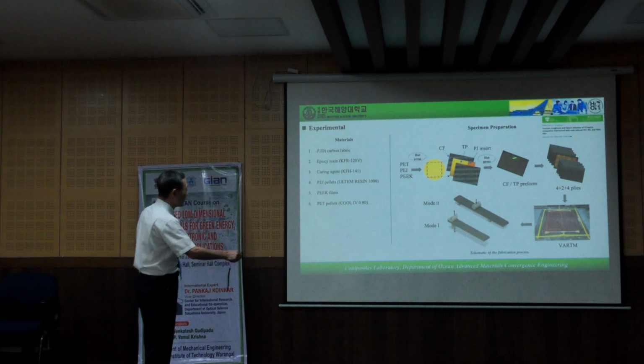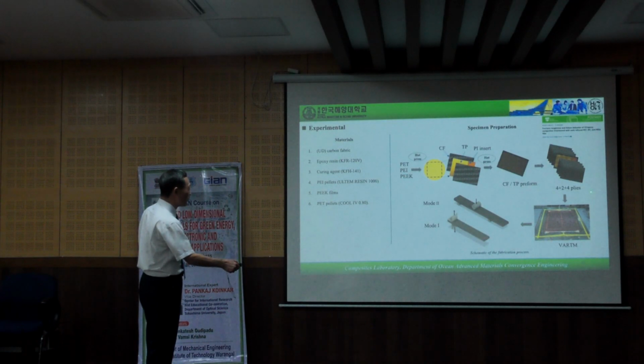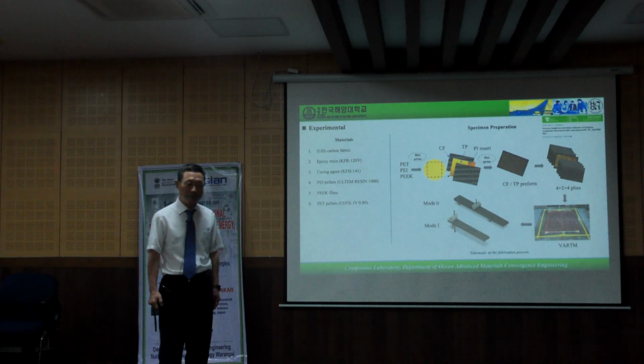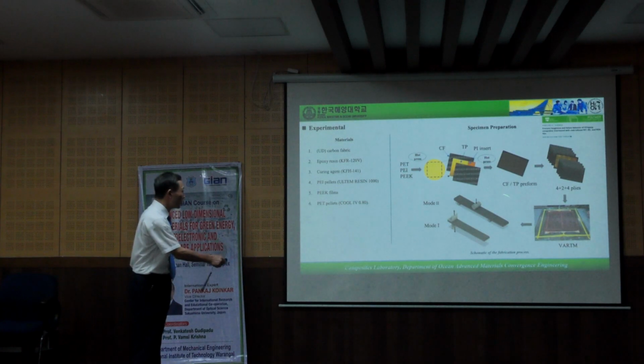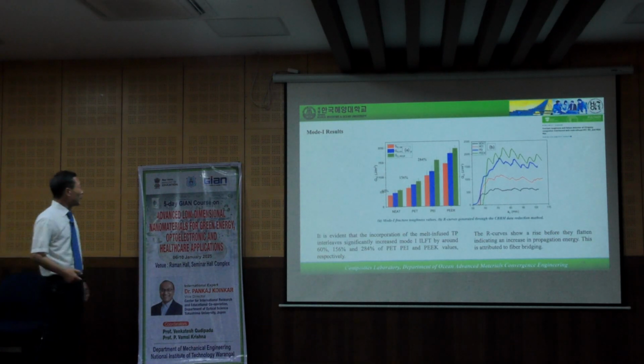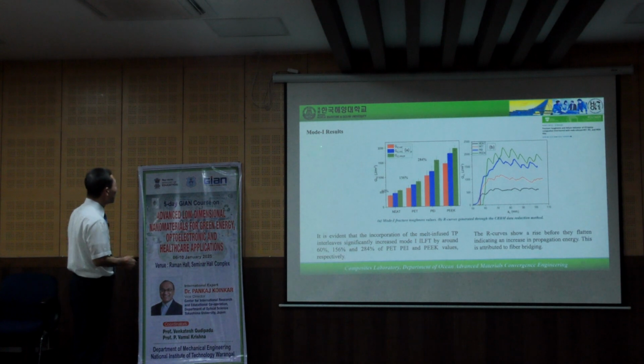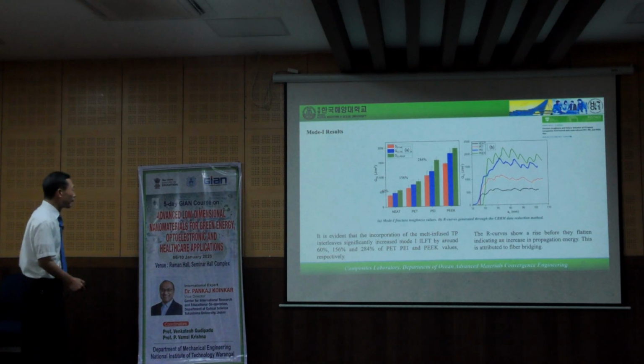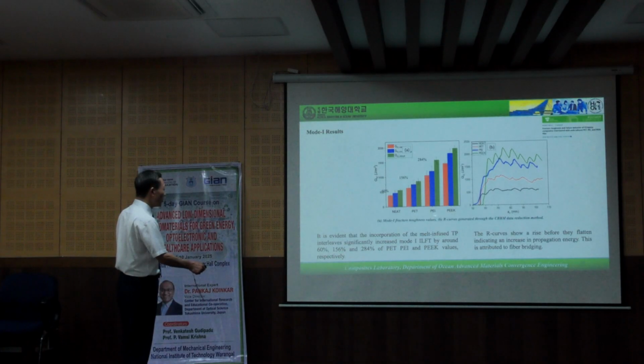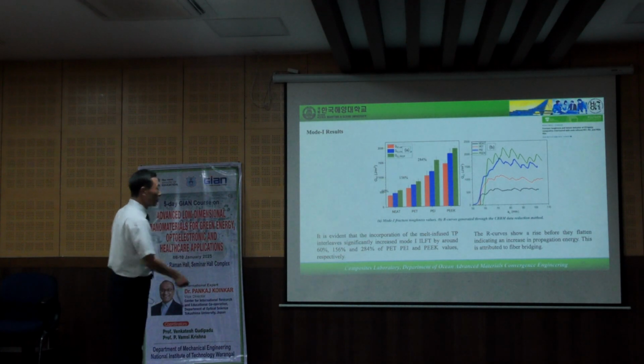We use the PET, PEI, PEEK. We prepared CFRP preform, and the stacking procedures, and we use the vacuum-assisted resin transfer molding. And finally, we prepared the mode 1 specimen and the mode 2 specimen. This is the result of mode 1. Again, the neat, PET, PEI, PEEK. The situation is like this.